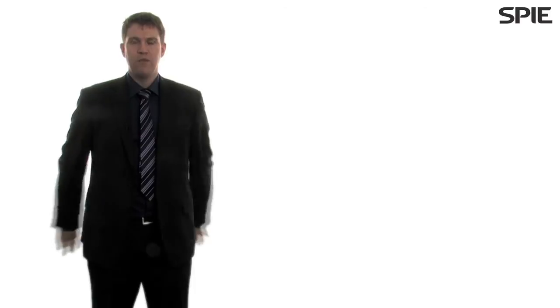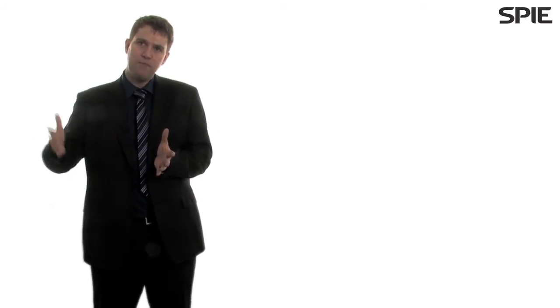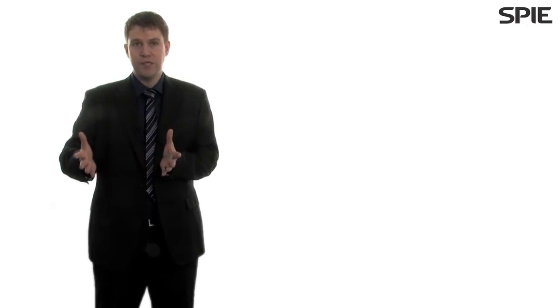One of the problems that you find when you look at diamond, particularly the polycrystalline first of all, thinking about the absorption around 10 microns, we are pretty close to the intrinsic absorption of diamond at that level. We can't keep pushing the absorption down and down. And yet if we get to a window that's taking more than maybe 50, 60 kilowatts, then even diamond starts to have trouble dealing with that sort of power.